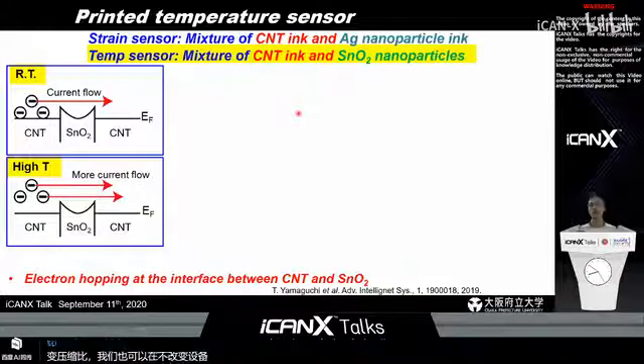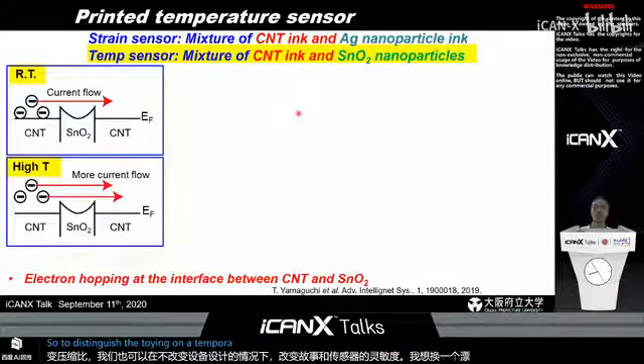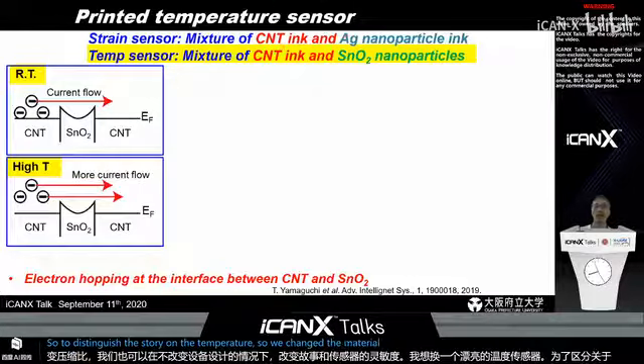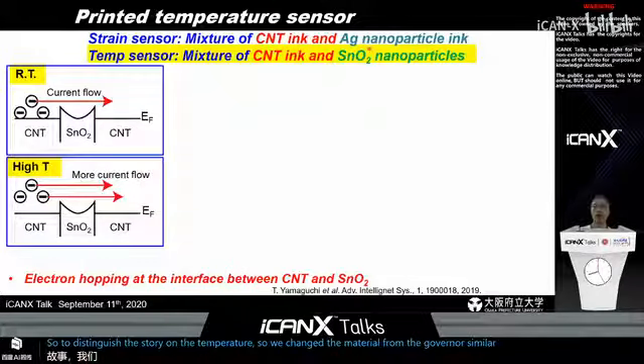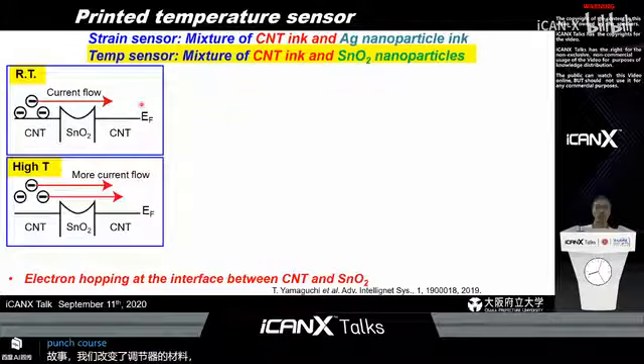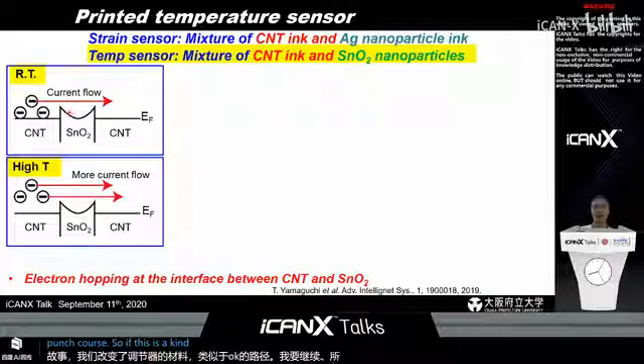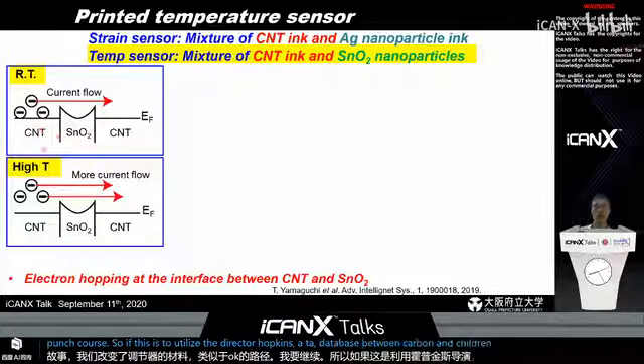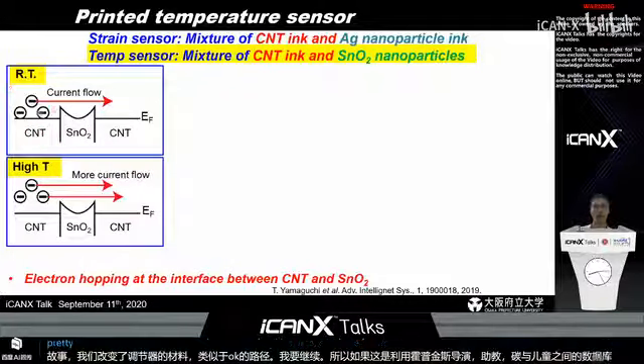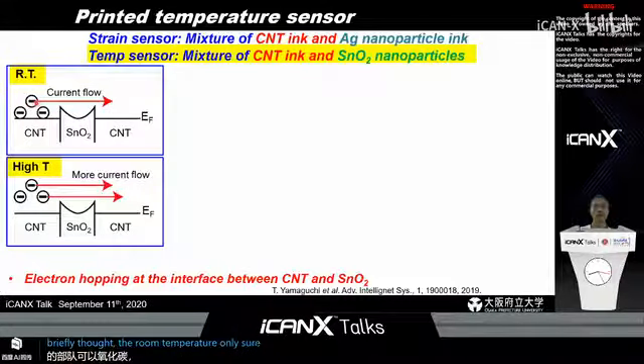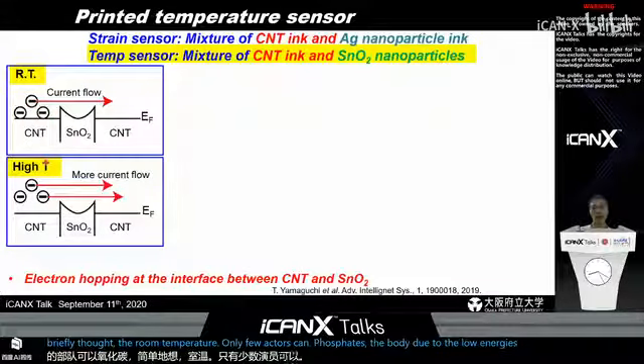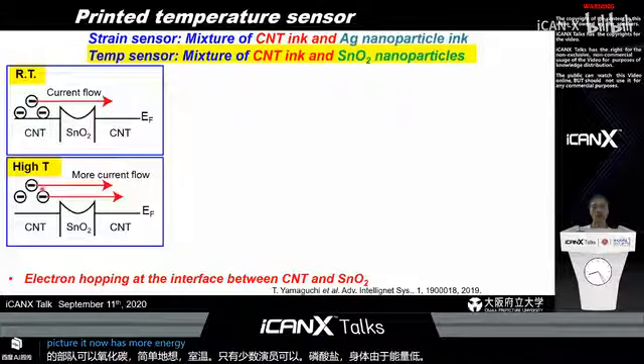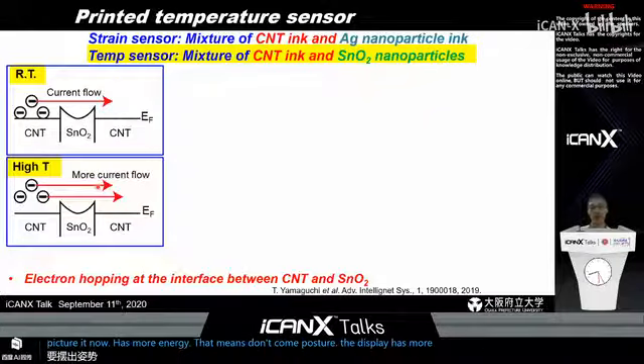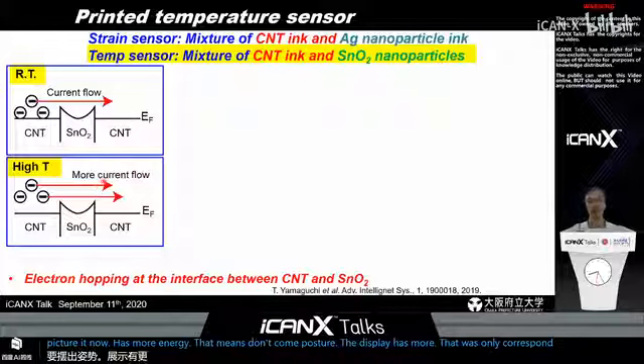To distinguish the strain and the temperature, we change the material from the silver nanoparticles to tin oxide nanoparticles. The sensing mechanism utilizes electron hopping at the interface between carbon nanotube and tin oxide. Briefly, at room temperature, only a few electrons can pass through this barrier due to the low energy. However, at a higher temperature, electrons have more energy. That means electrons can pass through these barriers more, which corresponds to lower resistance values.